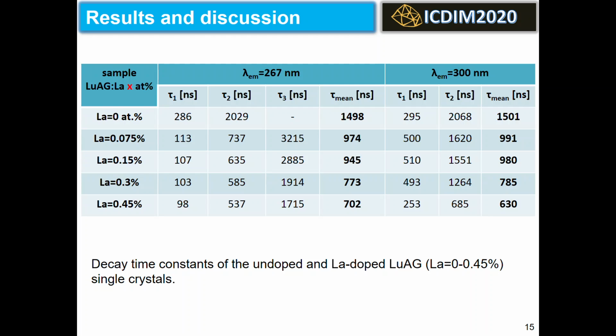The decay curves for undoped LuAG crystal recorded for emissions at 267 and 300 nanometers are similar with comparable fitting parameters. This observation confirms that the emission band, centered between 200 and 400 nanometers, is caused by at least two types of luminescent centers related to lutetium-aluminium antisite defects, namely the luminescence of excitons localized and bound at lutetium-aluminium antisite defects.